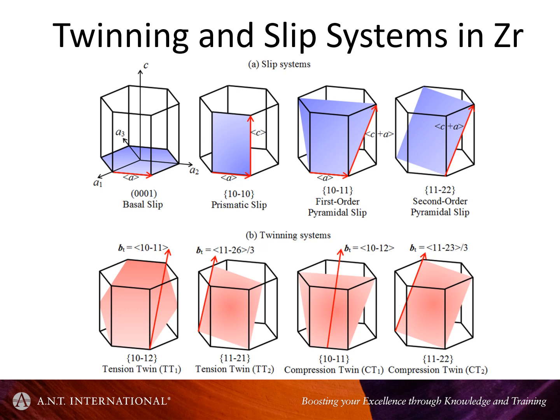Now for zirconium, zirconium is an interesting material in that there are lots of opportunities for twinning, just as there are lots of opportunities for different slip systems, because you have a range of planes which have a similar atom packing density, and so the variability in the shear stress needed to operate slip systems on these different planes is not a big spread. Depending on the stress state, you can generate all kinds of dislocations. Well, you can generate C component dislocations as well as A type dislocations on different planes. The planes inclined to the basal plane, the C plus A type dislocations.